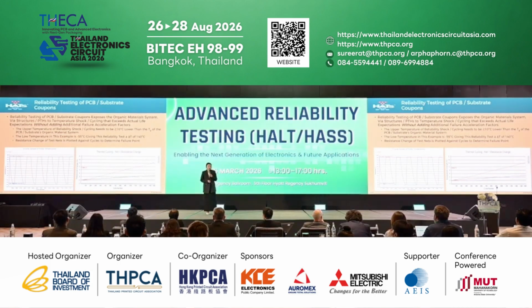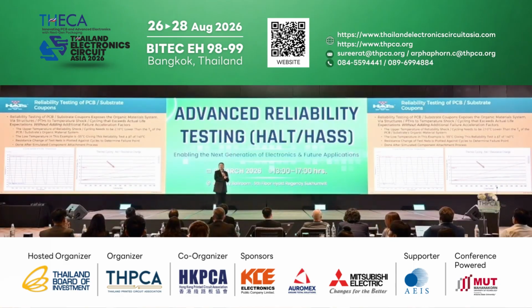For thermocycling, the low temperature is, in this case, on the graph, -55. This temperature is also very commonly used these days, especially for some of the data center or AI GPU companies. And this example of thermocycling is done after the previous assembly process survivability testing.